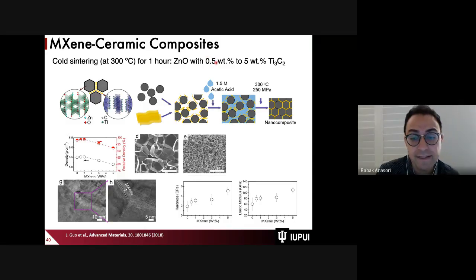The reason for that is we only need just 1 nanometer thick of these around the particles. Here's a good example. If you go beyond 1 weight percent of MXene, densification drops because then we get too many of these. So we can make the composites that right now we are making with the regular bulk materials of oxides with transition metal carbides. But instead of using 5%, 10% to improve the mechanical properties, we only use maybe barely 1 weight percent. So it doesn't change the density, it doesn't change the mass, but we can significantly improve the mechanical properties. So this is one of the big advantages.